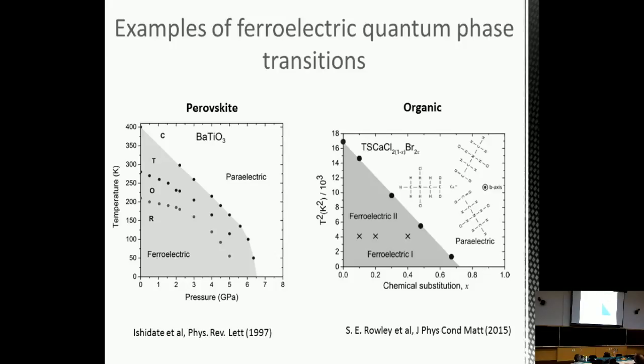I've got here some examples of ferroelectric quantum phase transitions in a diversity of different materials. So here we can see barium titanate that I was just speaking about. And with around 60 or 70 kilobars, you can tune this phase transition all the way to absolute 0, where it undergoes a quantum phase transition between two different ground states here. Here's another example in organic materials, tris sarcosine calcium chloride, where you can dope, in this case with chemical substitution. So doping bromine for chlorine suppresses the transition, and then around here at 0.7, there's a quantum critical point in this system.